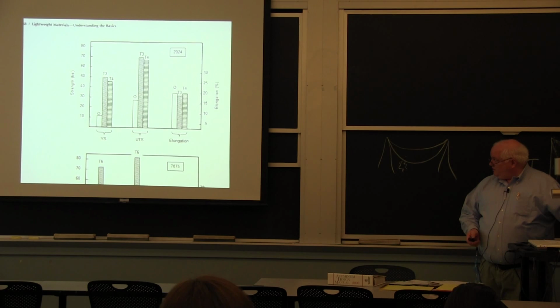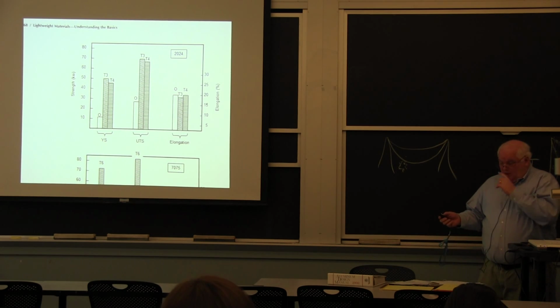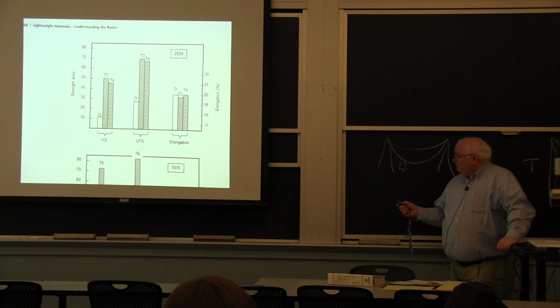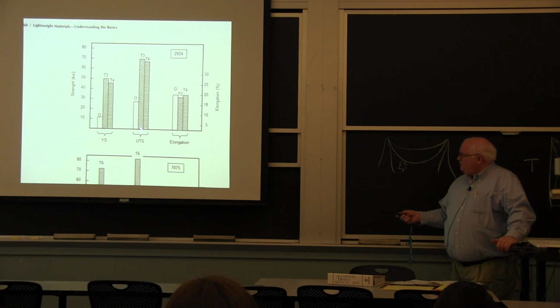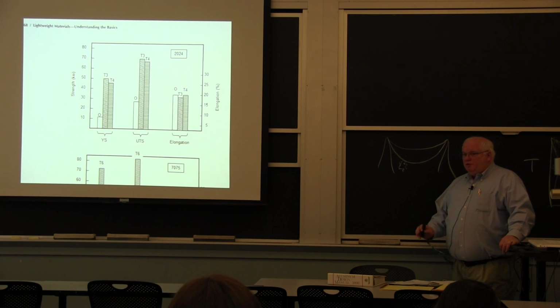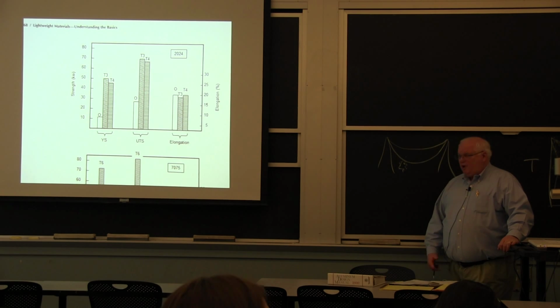If I look at the relative strength of some of these heat-treated alloys, this is 2024, the workhorse heat-treatable aluminum alloy from 1920 to 1950, and still used today. The annealed condition has a strength of 12 ksi. The heat-treated T3 condition, which is optimum strength, is over 50 ksi. T4 is like 5 or 10% less, but it has much better stress corrosion cracking resistance. This is yield strength, this is ultimate tensile strength, and here's the elongation. The elongation is about the same in all cases. They have pretty good ductility. Aluminum in general doesn't have the brittleness that steel sees from hydrogen and things like that. Hydrogen creates other problems in aluminum.